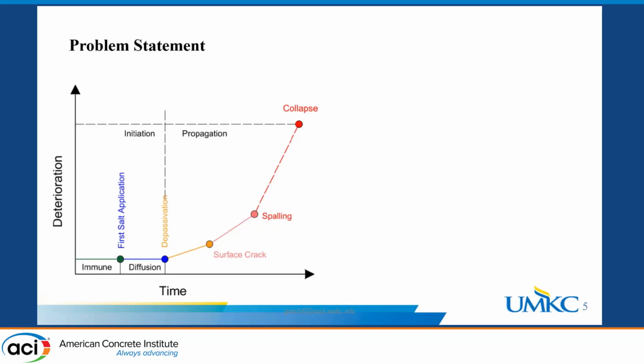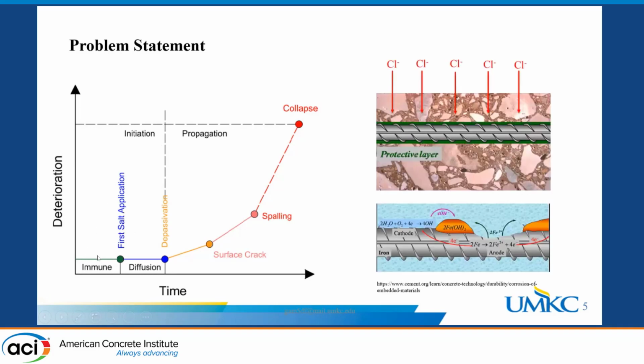If we look at most of the corrosion or deterioration models generated for predicting concrete service life, we can see that the concrete at the beginning is in an immune state. But once salt is applied for the first time, or the concrete comes in contact with marine water, chloride ions gradually diffuse through the concrete cover. Diffusion takes time and depends on the concrete cover depth. If the concentration of chloride ions at the steel reinforcement reaches the critical chloride threshold, the chloride depassivates the protective layer and exposes the steel bars to corrosion. Once there is water and oxygen, the corrosion initiates.